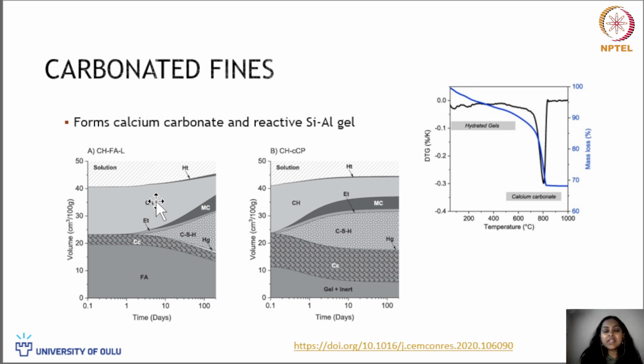But the final result that has been seen is that the calcium hydroxide that is left in your hydrated cement turns into calcium carbonate. That's one thing. Another thing that was observed in the studies is that your silica and alumina become a reactive gel that helps in improving the reactivity of these carbonated recycled concrete fines, which then can be easily used as a supplementary cement.